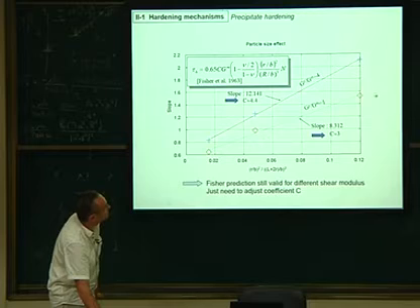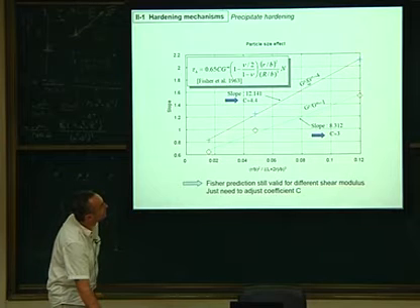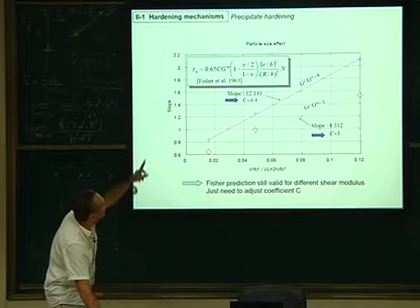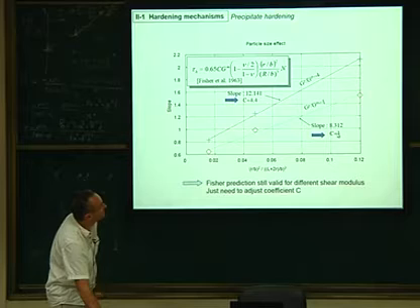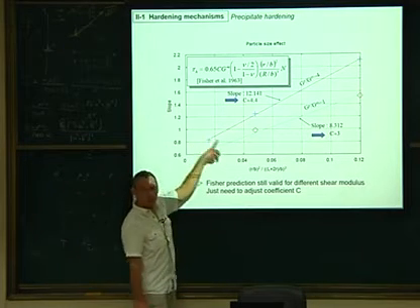You can still apply such a fit, except that the prefactor C here has to be adjusted. So if you adjust this in the case, for example, of such a ratio of modulus between the matrix and the particle, 4 times bigger, then C is 4.4. If you have the same moduli, which was the equation here, you have the slope, which was here, C is equal to 3.